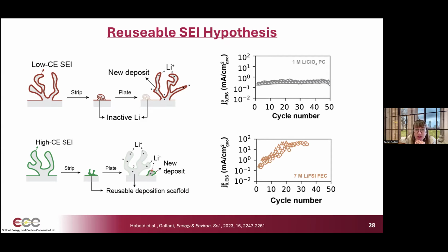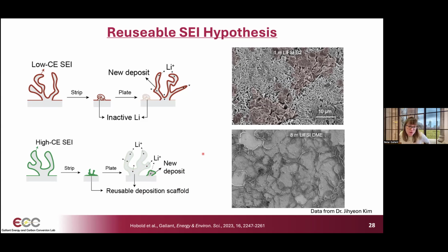In other words, you continue to add to and increase the active surface available for lithium exchange as you continue to add to the scaffold, and then eventually it percolates and you've formed a stable scaffold and you see a leveling off. So at the time, this really was just a proposal, with a schematic to go with it. But I will say in time, we've been focused much more on validating this idea, and we've obtained evidence that this really seems to be sound.